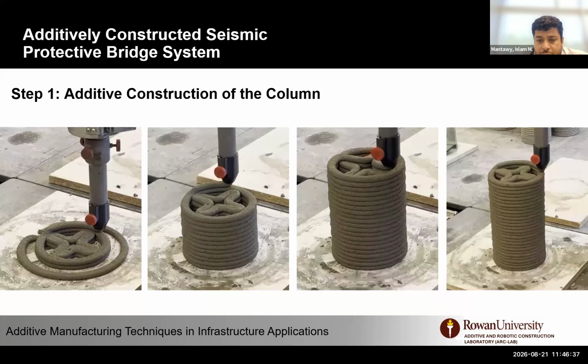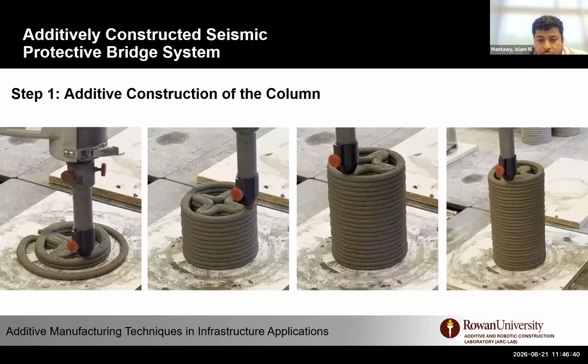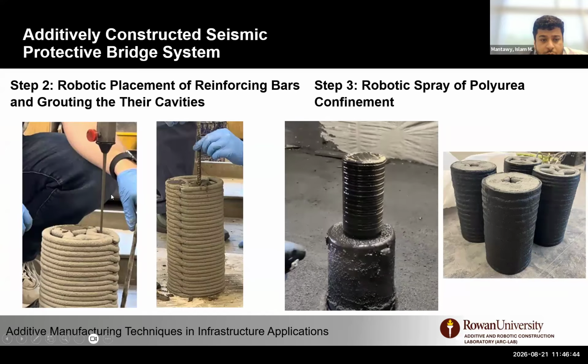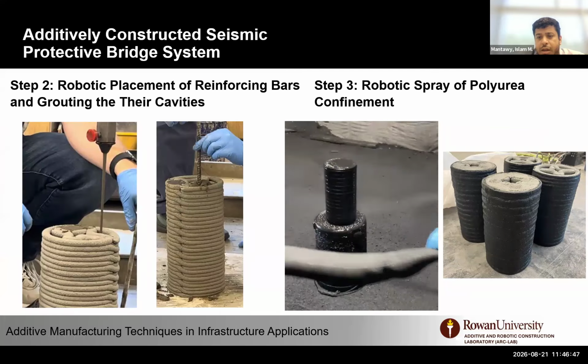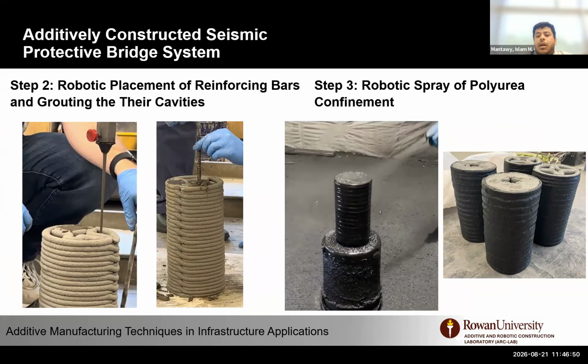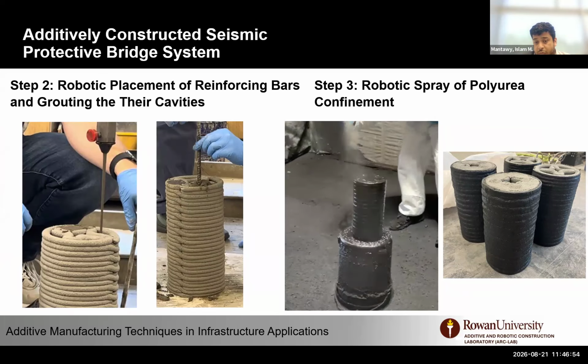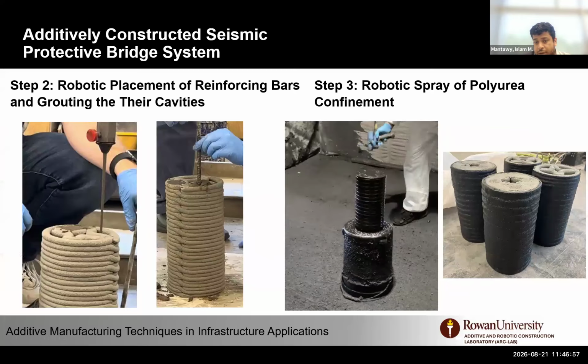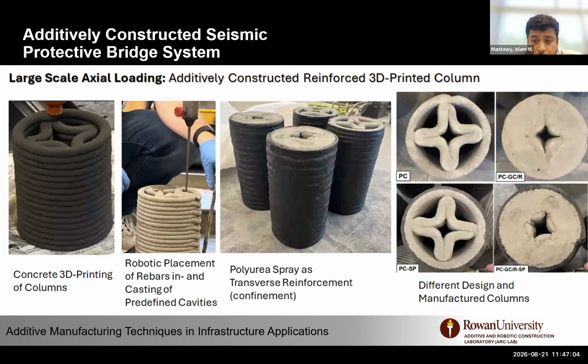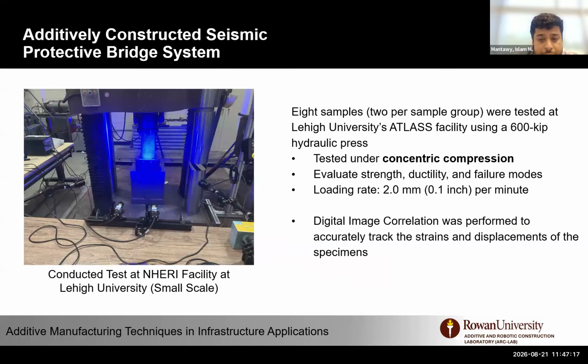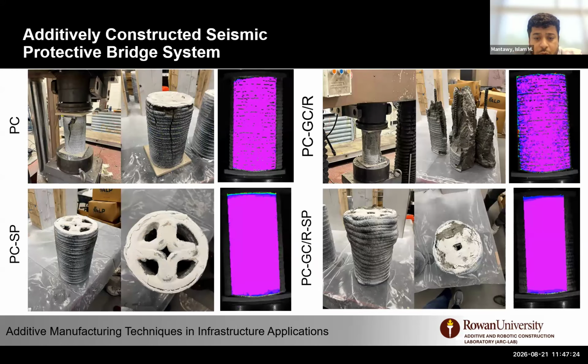We did the stub columns to test the capacity of those columns. We also did integration of rebar and robotic casting of those cavities, and we used the polyurea material for confinement, which is good for impact and can also give us a benefit for confinement as an external coating. So you can see here we have 4 columns. We tested those columns where we have only the printed shell, printed and grouted, and rebar printed with the spray, or all. And we tested all those columns also at Lehigh University last winter, and we were able, as you can see here, to see the failure modes for each of them.